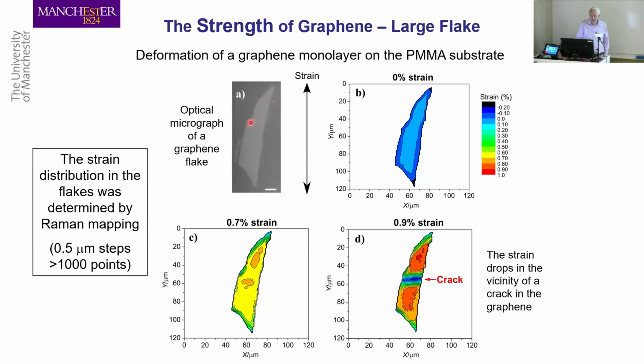So we start off in the undeformed state, 0% strain. And you can see here, this is our sort of rainbow chart here of strain. You can see that it's fairly undeformed. Then we go to 0.7% strain. We start getting hot spots in the material. And then at 0.9% strain, we get hot spots and a blue area here where we've had a crack. So we've actually broken the flake. We've actually done a fracture experiment on a single layer of atoms. We've looked at the strain needed to break a single layer of atoms.